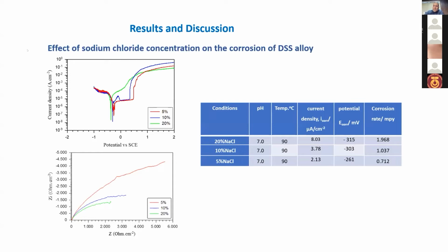Now, at first, we investigated the effect of sodium chloride concentration on the corrosion resistance of both alloys. The solution was prepared in 3 concentrations: 5%, 10%, and 20% of sodium chloride. And in this test, the temperature and pH were set at 90 degrees centigrade and pH 7, respectively.